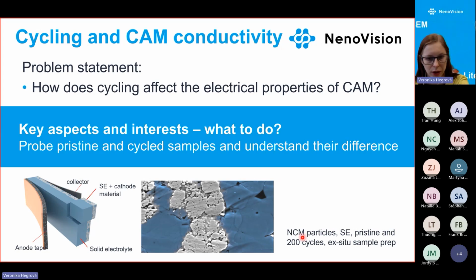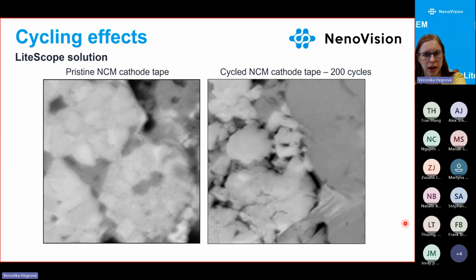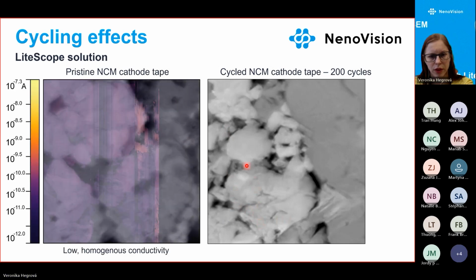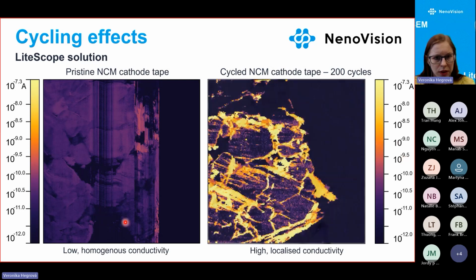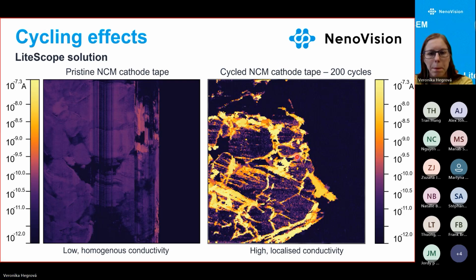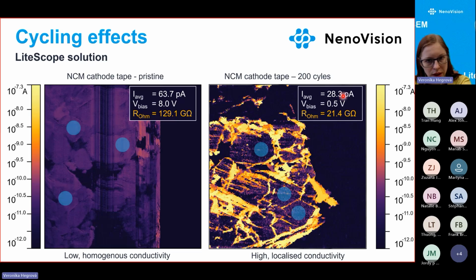The analyzed sample is nickel, cobalt, manganese in solid electrolyte, and we have a pristine and a cycled tape. If we have a look at the pristine and cycled tape, we already see some differences even in the SEM. The pristine one has, I would say, a quite homogeneous structure, unlike the cycled one, where there are already some cracks. If we compare the conductivities, we see the pristine one has low homogeneous conductivity. On the other hand, the cycled one has high localized conductivity at the edges and lower conductivity in the middle part.